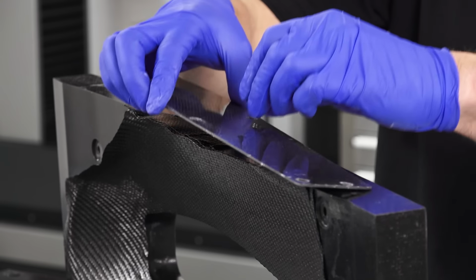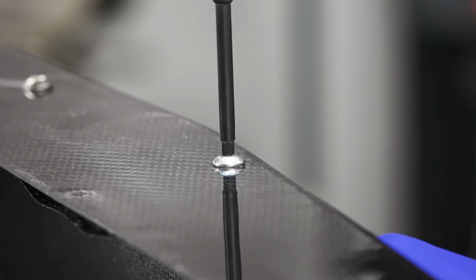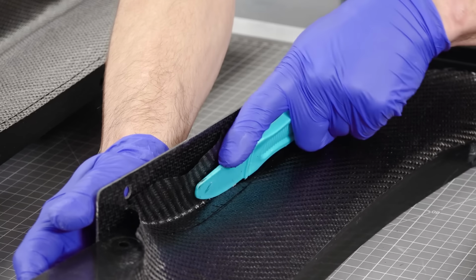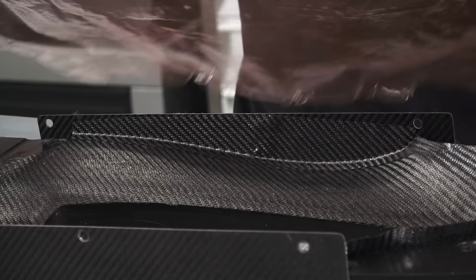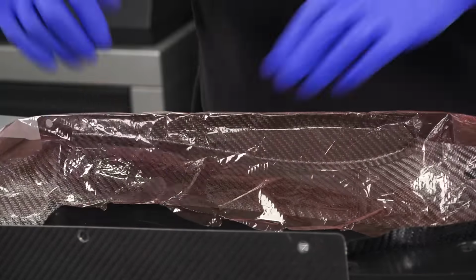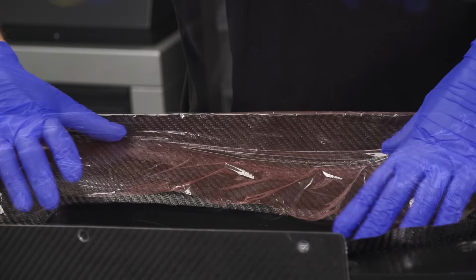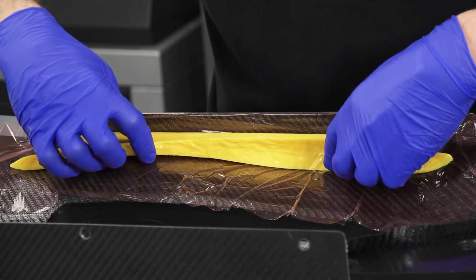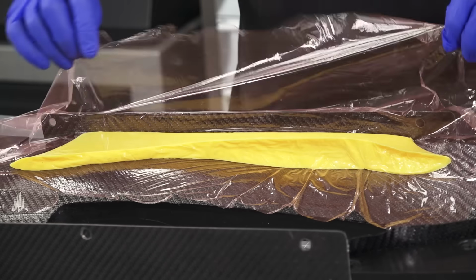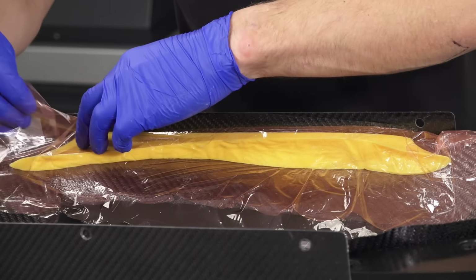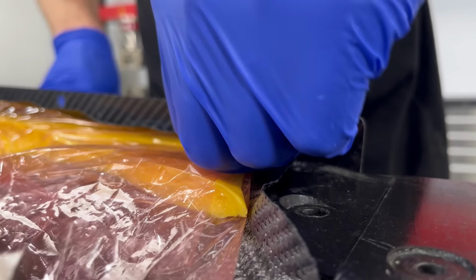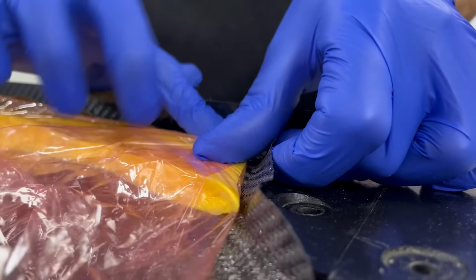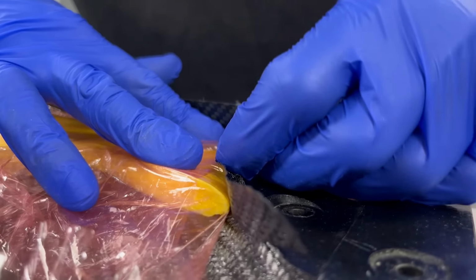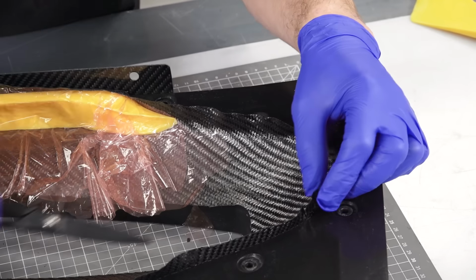So let's now take a look at getting the intensifiers into here and getting the moulds closed. First, I'm attaching my barriers and making sure that the prepreg is properly pushed up against them. Before positioning the intensifiers, release film needs to be applied. This allows the inserts to be easily removed later and also prevents any silicone contamination affecting the part. Once in place, the lap of carbon fibre can be then carefully folded over the intensifier, ensuring that it will be correctly positioned when we close the mould.